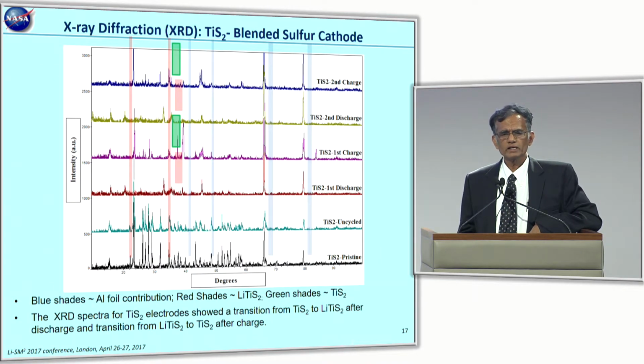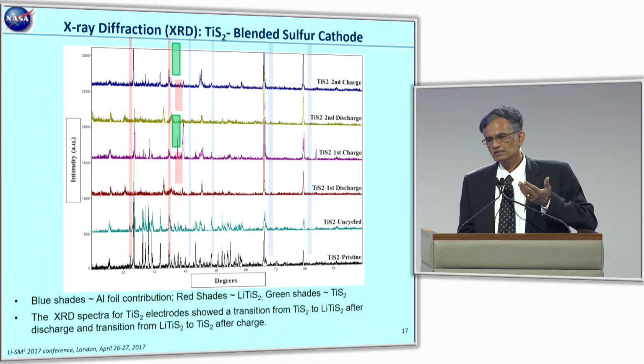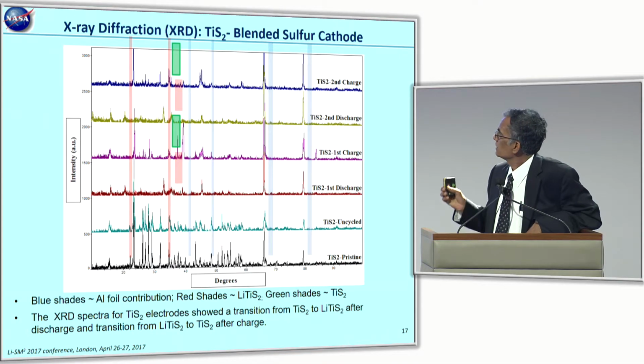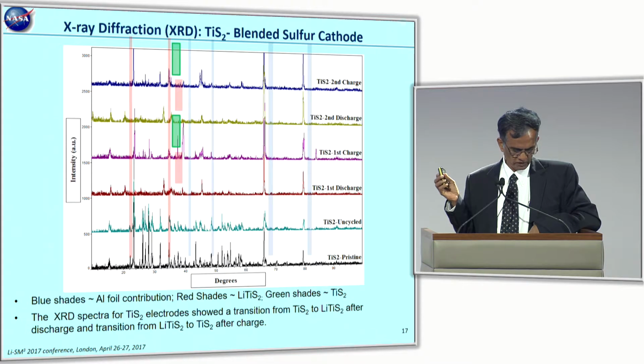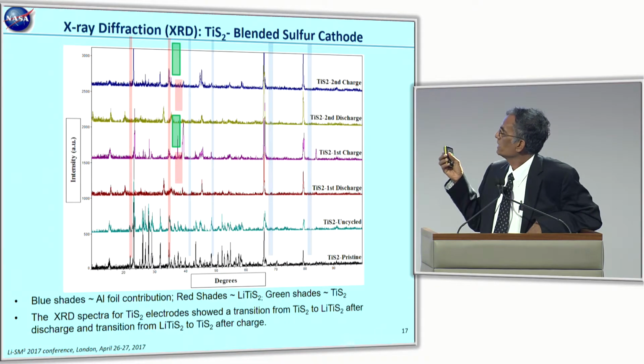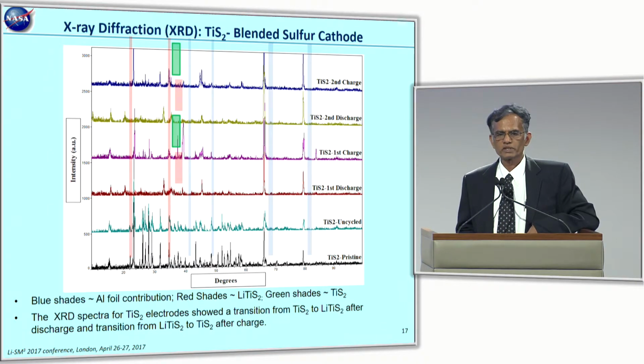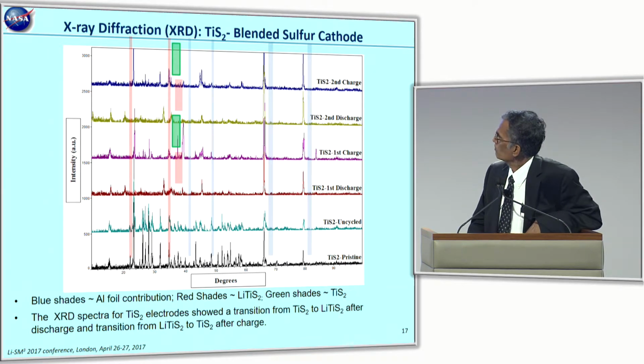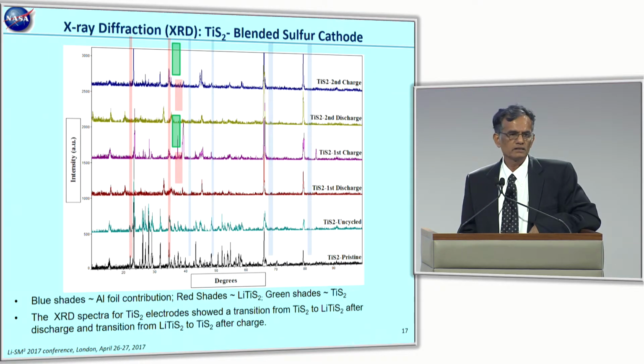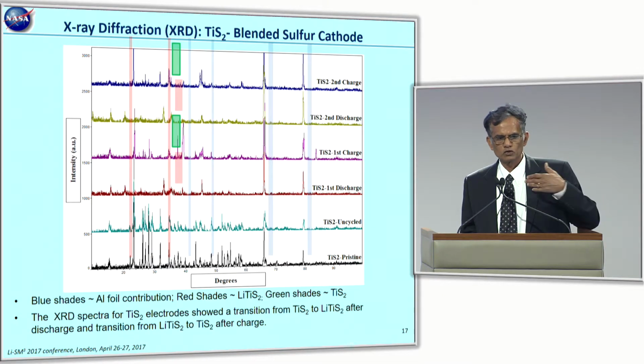And we started trying to do some experiments here, trying to understand what is actually happening. Here it is, the XRD, the X-ray diffraction of this TiS2 at different stages. Starting from the bottom, you have a pristine uncycled material, then one discharge, the first charge, and going all the way to the second charge. You can see here the green and red shades represent the peaks corresponding to TiS2 lithiated and delithiated phases. So there is a clear redox transition of TiS2 as you cycle the sulfur cathode back and forth.